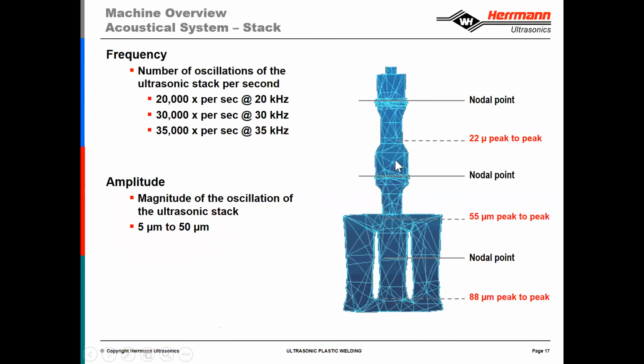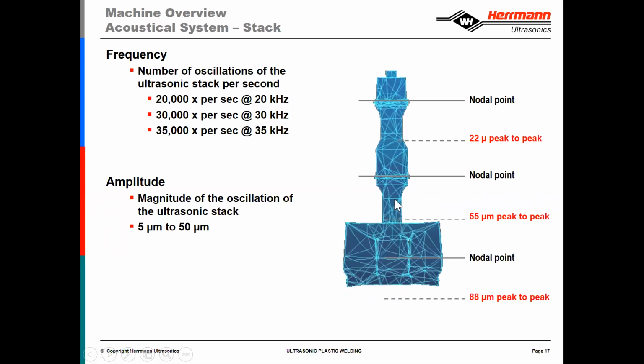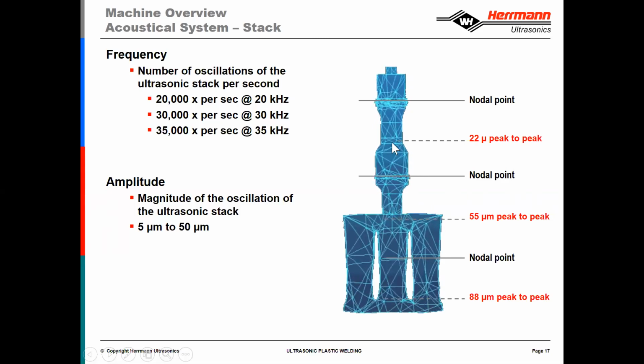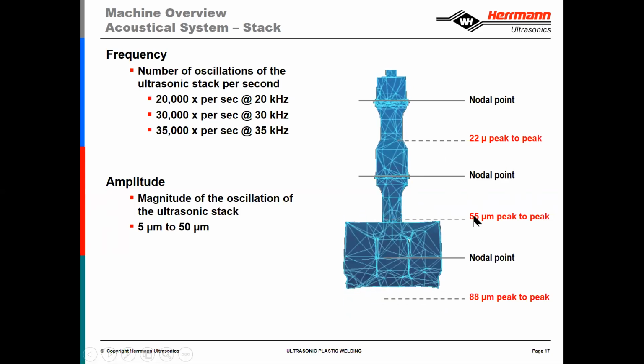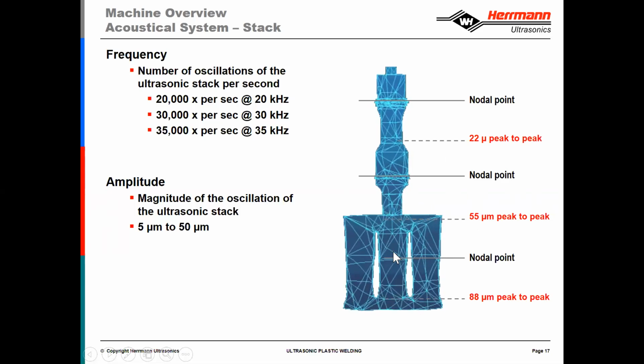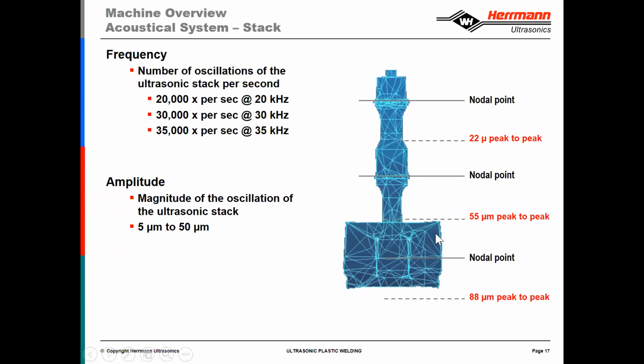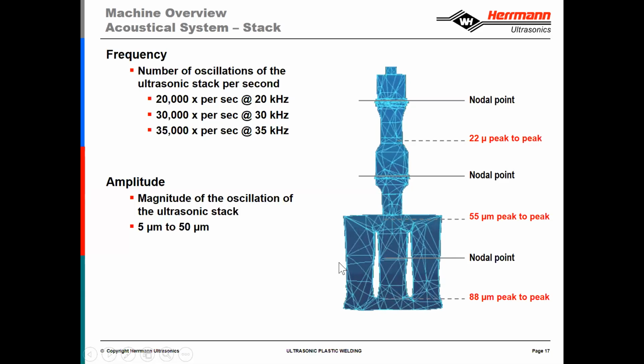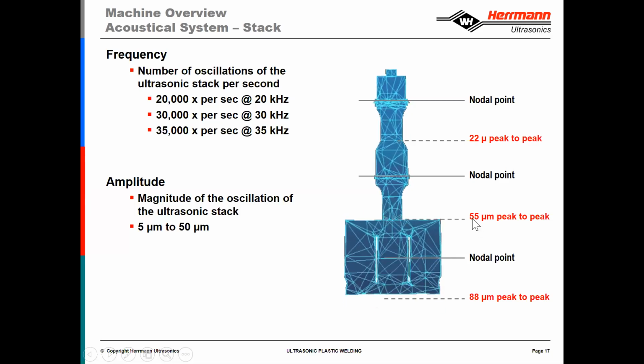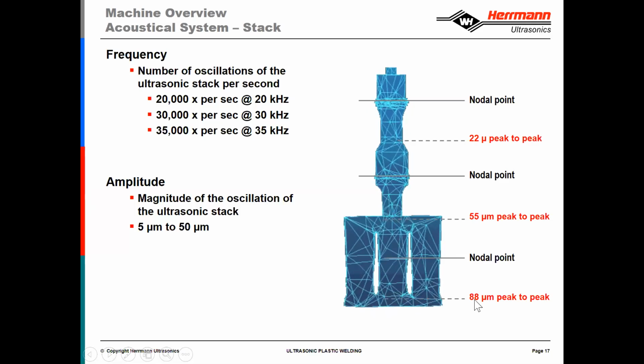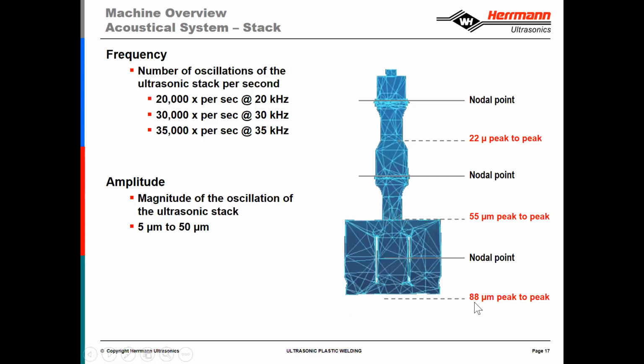And then the booster, because of the nature of its design, has the driving mass above the nodal point and the driven mass below the nodal point. You can see that there's a discrepancy: the driving mass is larger than the driven mass. Therefore, more amplitude is created at the face than was input at the back. So from 22, we go to 55 microns. It's not visible here, but if we were to turn the Sonotrode 90 degrees, you would see that again the driving mass above the nodal point is larger than the driven mass below the nodal point. So again, we have a gain ratio. The amount of mass above is larger than the mass below. Therefore, we go from 55 microns of peak-to-peak input to 88 microns of output, or conversely, 44 microns zero to peak.